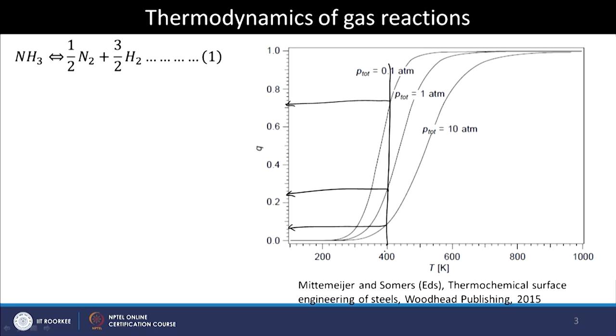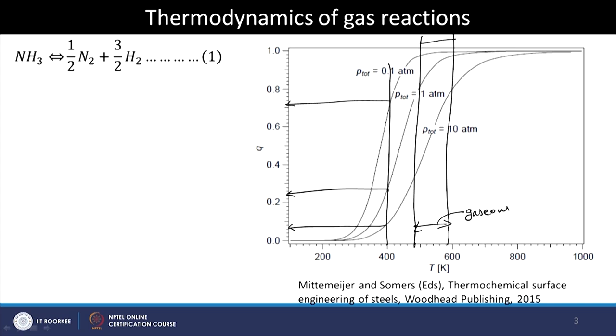At the normal temperatures of interest for nitriding — usually in the range of 450 to about 580°C — this is the band where we carry out gaseous nitriding. If you look at this window operating at one atmospheric pressure, these values show that more than 80% of ammonia has already dissociated. That means, in your reaction chamber for nitriding, thermodynamics predicts that at a given temperature you will have largely decomposed ammonia, meaning large amounts of N2 and H2 in the reaction chamber.